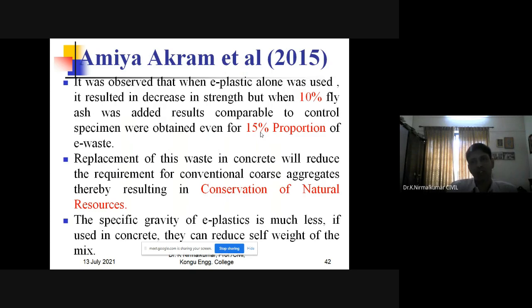Then he observed that with 10% fly ash added, results compared to the control specimen were obtained even for 15% proportion of the e-waste. Replacement of this waste in the concrete reduces the requirement of conventional coarse aggregate, and as a result, even the natural resource can be conserved. The main thing we have to know is the specific gravity. The specific gravity of the e-plastic is much less. This is a very big issue.